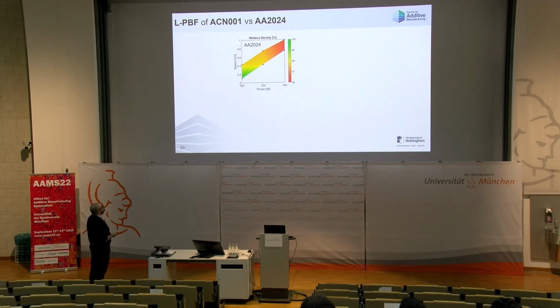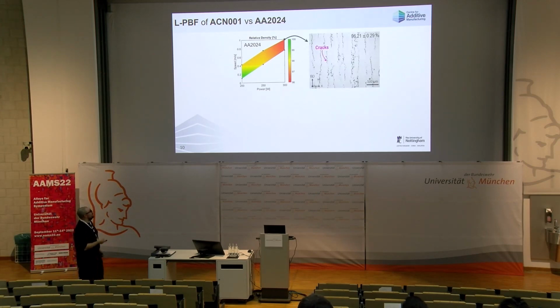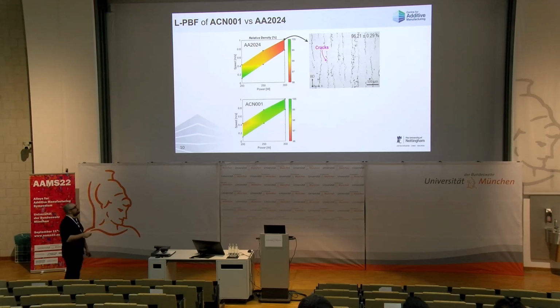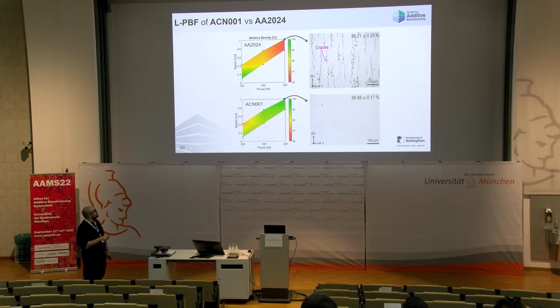When we print 2024, as you can see here, when you compute relative density in the high power, high speed regime, you have very good consolidation, because this is the kind of microstructure we have. There are a lot of cracks, of course. But when we printed our alloy, what we found is that there is great stability as far as consolidation is concerned, and with a speed which is 10 times faster, you can achieve way better consolidation without cracks.